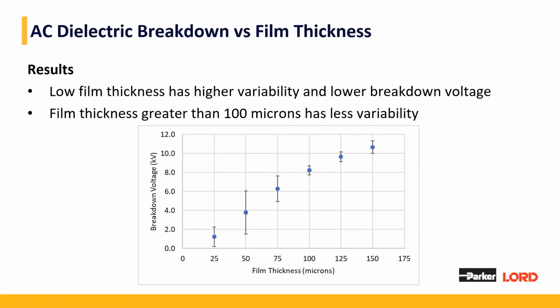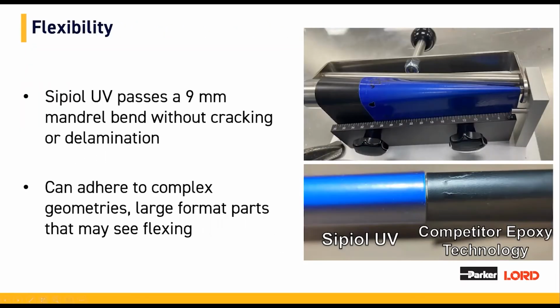This test is measured until the applied voltage caused a breakdown. There is not a voltage limit as there was for the DC hypot testing. This plot demonstrates similar results to the hypot testing, with thinner films having lower breakdown and higher variability. Depending on application needs, we would make a similar recommendation to use 100 microns minimum for the best and most repeatable results. Sipiol UV is very flexible and passes a 9 millimeter mandrel bend without cracking or delamination.